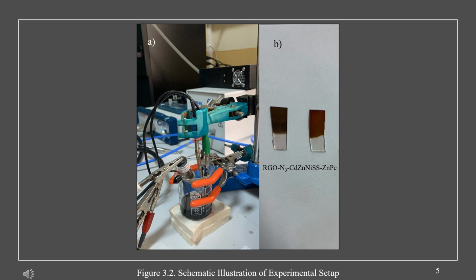The three-electrode system was set up. For this, the electrolyte was placed on the bench, saturated calomel electrode was used as the reference electrode, and platinum was used as the counter electrode. These electrodes were washed with distilled water before use.